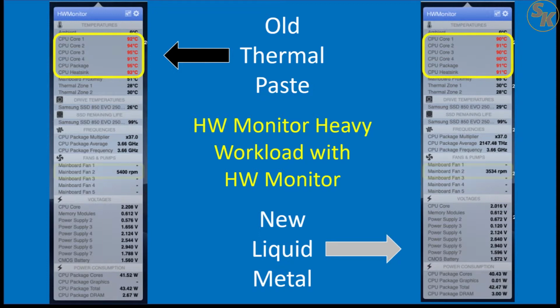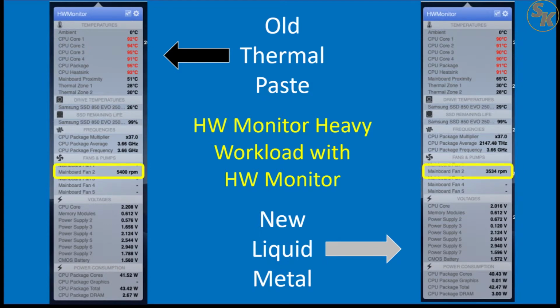The big difference was the fan RPM under a heavy workload. When the processor had the old thermal paste, the fan speed stayed between the 5400 to 5700 RPM range to combat the 90 degrees Celsius processor temps, which caused the obnoxious noise. With liquid metal, while the temperature was in the 90s, the RPM stayed within the 3500 to 3800 range, and with that came a reduction in fan noise, but not as much as I imagined.